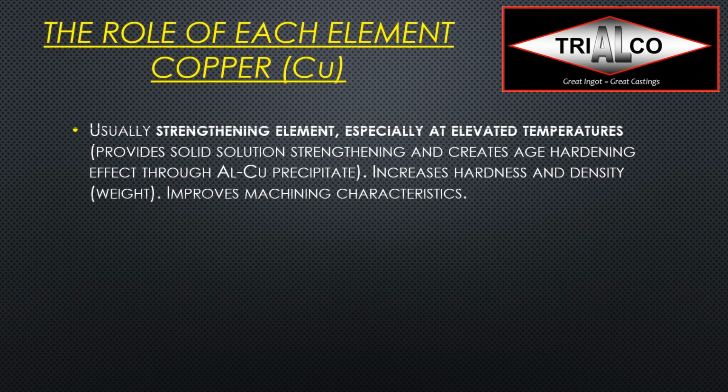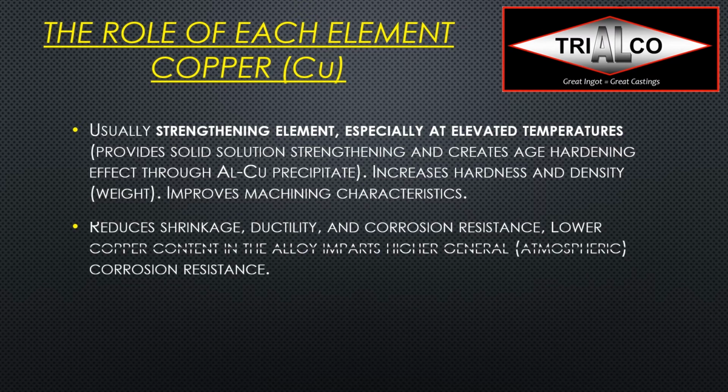So now let's go into the role of each element very quickly. Again, copper, it's a strengthening element. It's relevant at elevated temperatures. So if you watched our webinar on alloys, we went into more depth regarding this. It also reduces shrinkage, ductility, and corrosion resistance.